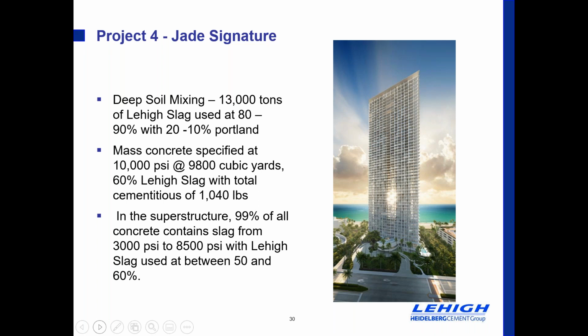That was 13,000 tons of slag used at between 80 and 90% and 20 to 10% Portland. That range was simply, I'm not quite sure why they settled on two different regions. I think they were concerned about early strength. So some of the edges were done at 80, but the center part of the project was all bumped up to 90%, 10%.